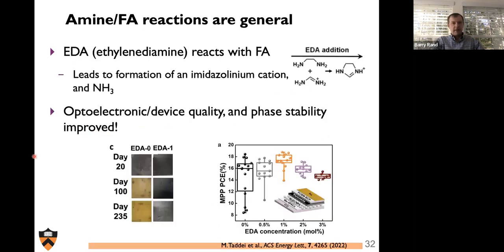Also recently, work out of both Seth Marder's group as well as David Ginger's group picked up on this interaction between amine and formamidinium. They used ethylene diamine, which, of course, if you've been listening to the last few slides, will react spontaneously with formamidinium. In this case, it leads to the formation of this imidazolinium cation as well as ammonia. And it's unclear to me whether this imidazolinium cation finds its way into the final film, or if it's just a happy spectator with regard to the overall process, but it does lead to improvements in the phase stability of the final film and also to the performance of these devices.